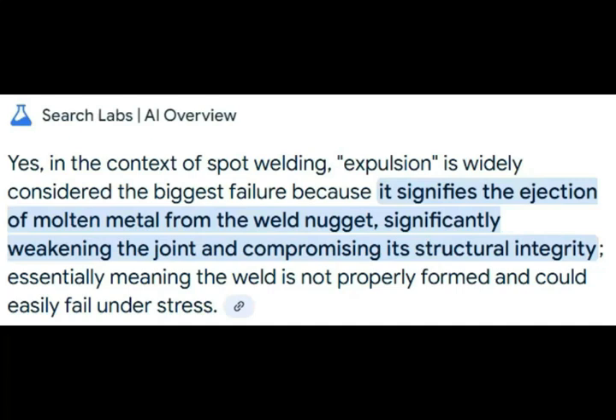Yes, in the context of spot welding, expulsion is widely considered the biggest failure because it signifies the ejection of molten metal from the weld nugget, significantly weakening the joint and compromising its structural integrity, essentially meaning the weld is not properly formed and could easily fail under stress.